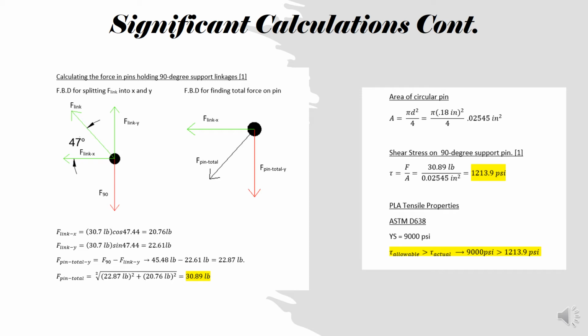Next we calculated the area of the circular pin and then found the shear stress using tau equals force over area, and we got 1,214 psi roughly. We compared it to the yield strength, and likely it'll be a lot lower because it's in tension. We were well under that, with a factor of safety of 7, so we would assume the device was safe, and we were going to verify that after testing.